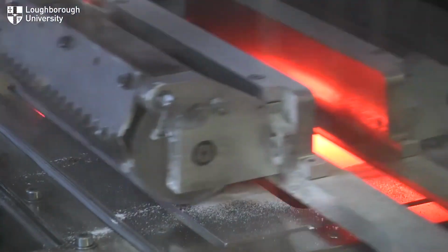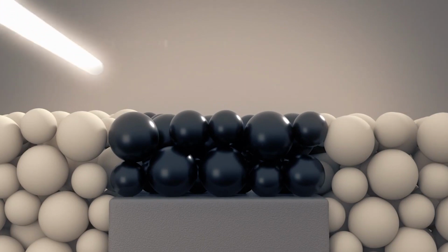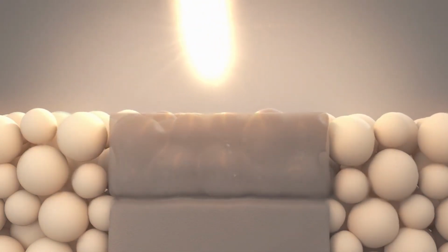You don't have to worry about the cost and time of post-processing and effects of those support attachment points on part quality. There are also a couple of new exciting powder bed fusion technologies for polymers that are variants on what we know about SLS. They're called high-speed sintering, a technology originally developed in the UK by academics there and now being spun out by companies including VoxelJet, and multi-jet fusion, a technology that's brought onto the market by HP, the same HP that we know for leading in 2D printing. Both of these techniques use infrared lamps instead of focused scanning lasers to fuse the polymer powder, and in order to use an infrared lamp that exposes the whole build area at once, the techniques first deposit by inkjet printing an ink onto the powder that determines where the powder absorbs that infrared light and therefore melts together.